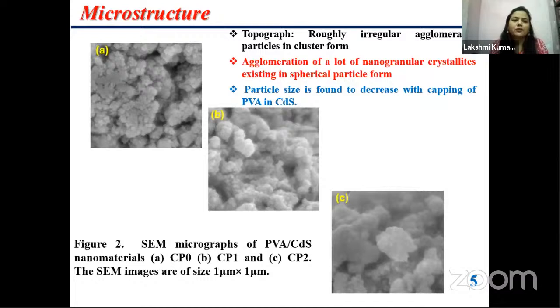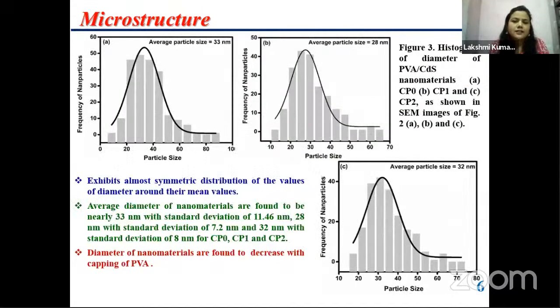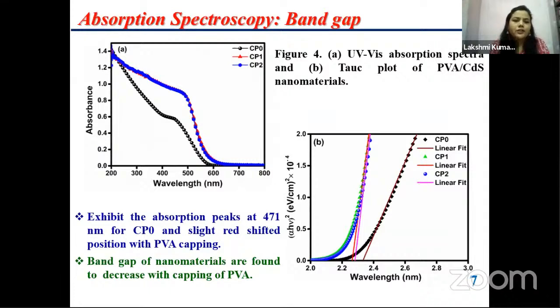After that, we have studied its microstructural property, and from the microstructure we can see that all samples have roughly irregular agglomerated particles in cluster form, and some agglomeration is enhanced after capping. And also we can see the particle size somehow decreases after capping. For getting more insight into how much the particle size decreases, we have also plotted its histogram, and we can see the histograms exhibit almost symmetric distribution of diameter values around their mean value, and all samples are almost similar, but their average diameter and standard deviation vary, which I have mentioned here. And we can see that the diameter of nanoparticles is found to decrease with capping of PVA.